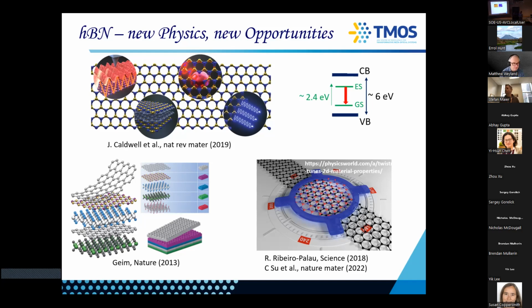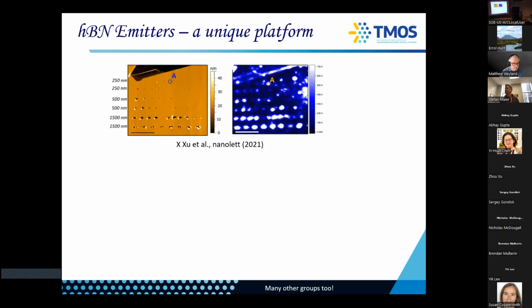And before I go into our results, I want to show you two very nice works that I personally really like about HBN and what makes it unique, unlike other 3D systems that would also have single photon sources. One of them is from the group of Shalaev, and here they show that if you exfoliate a very thin HBN, you can go with an AFM and physically scratch it, and everywhere you scratch, you generate an emitter. That's something you cannot really do with any other material. If you just scratch your silicon carbide, you're not going to see anything.